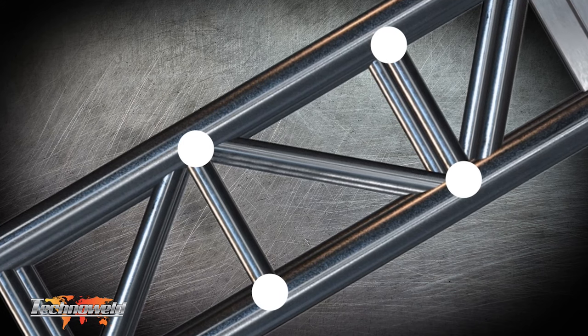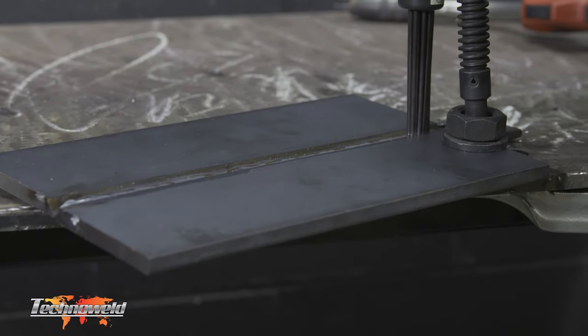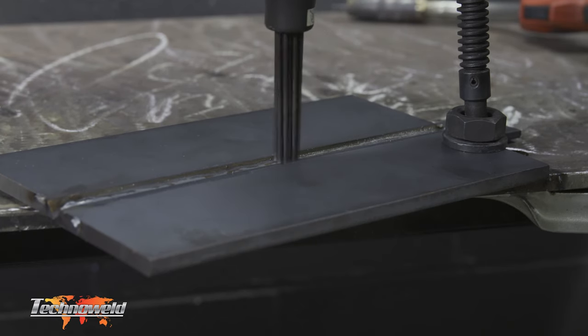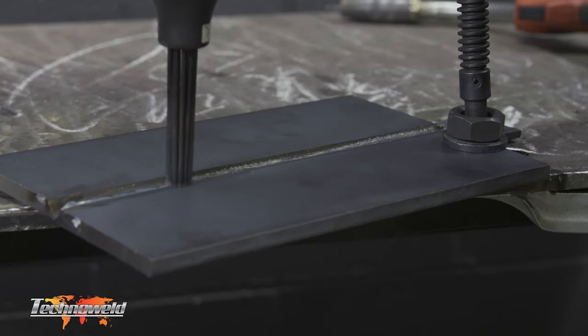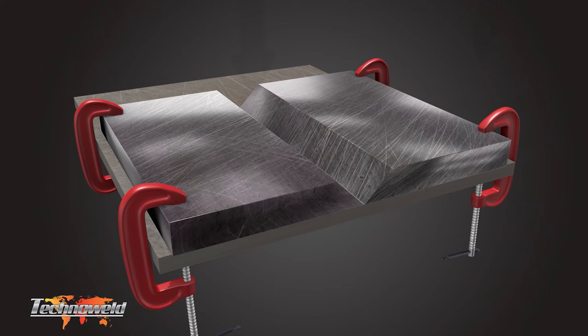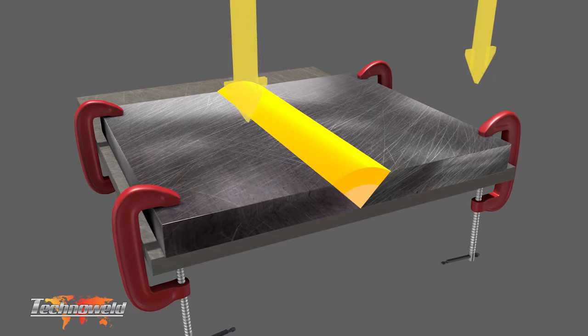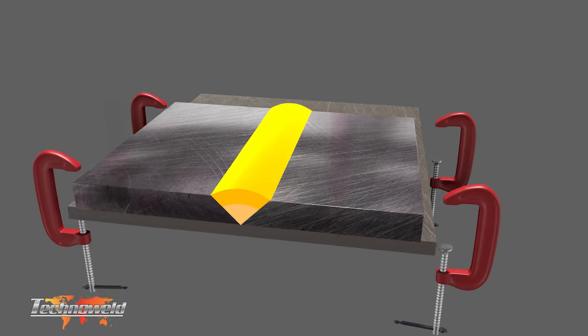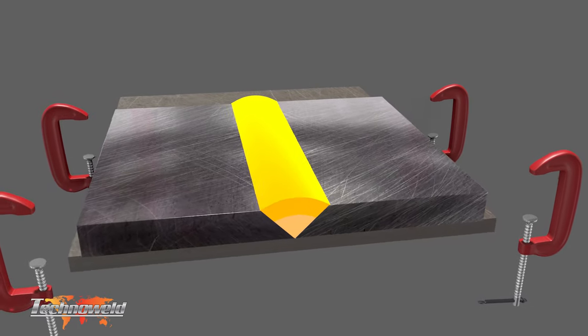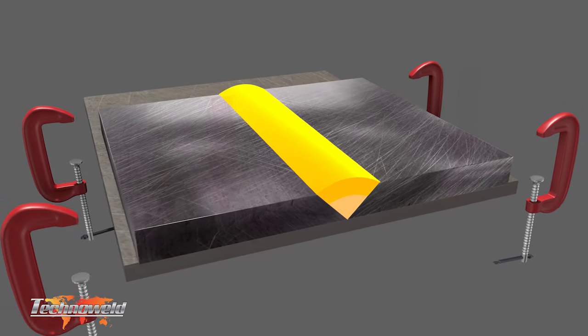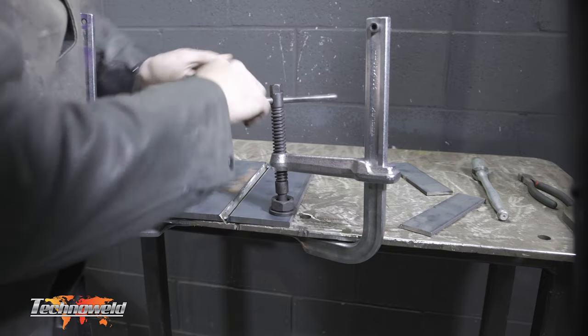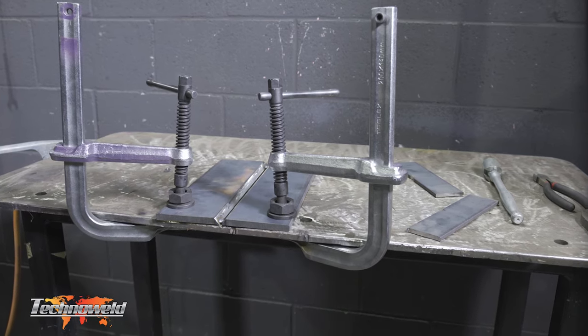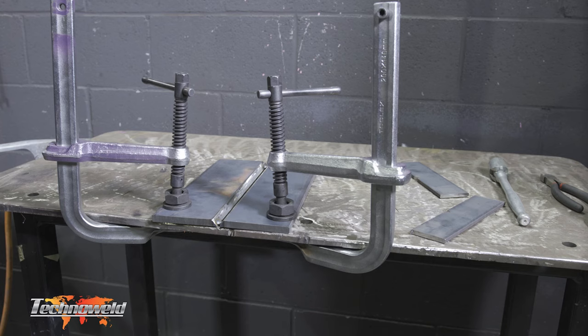There are many other methods to minimize or counteract distortion. One is peening the weld bead. Peening the weld stretches it to reverse the effect of the contraction on cooling. It also relieves residual stress and thus reducing distortion. Fixtures or other restraints can also be used to prevent distortion. In this example you can see that the restraints are putting downward force on the metal, preventing it from moving at all. When we release the clamps you can see that there is virtually no distortion. However, any time that a physical restraint is used, it puts additional stress on the material you're welding. By preventing the metal from being able to naturally expand and contract, you are increasing the stress in the weldment. Restraining the metal in this way can cause other issues such as movement during galvanizing or potentially even cracks along the weld or heat affected zone. For this reason, restraints should only be used in certain applications and with certain materials.